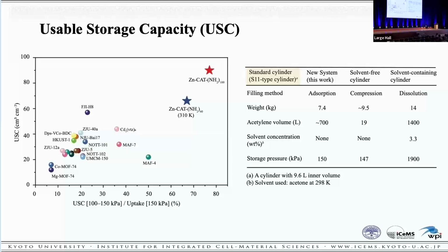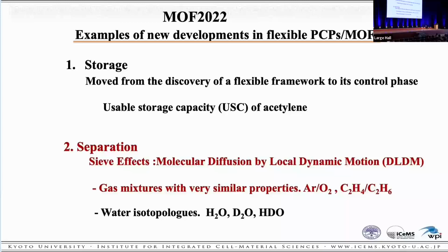We have obtained a fairly high usable storage capacity so far. The next challenge is to address the issue of separation by flexible MOF. We propose a new mechanism to control the diffusion rate of guest molecules using local dynamics, also in flexible MOFs. We call this molecular diffusion by local dynamic motion, DLDM.